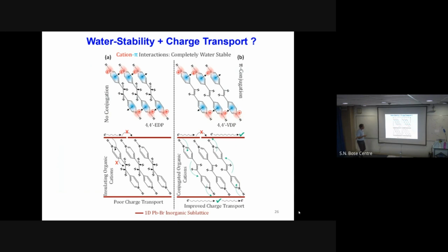So this is the situation that I presented just now. This is the organic molecule, and if I consider this is the inorganic part, and this is the organic linker between the inorganic. So we thought that if we can introduce a double bond here, so from here we are going to the next sample that is just having this double bond. So if I have a double bond here, then it establishes a pi conjugation through the molecule, and hopefully that will increase the electrical transport between the two. And with this idea, then we made the next sample.